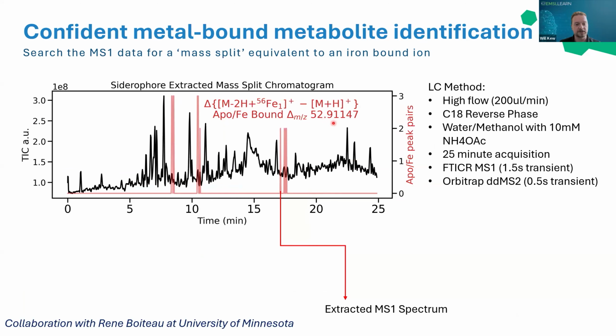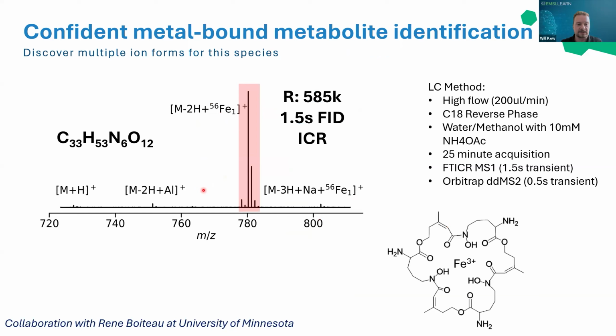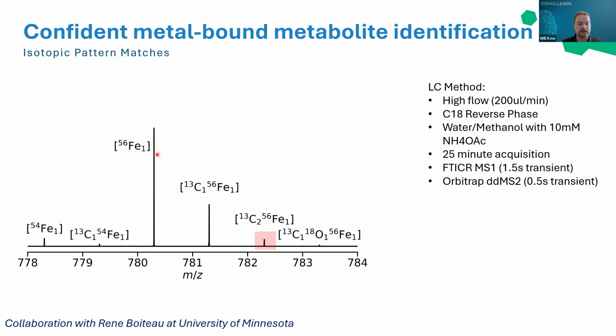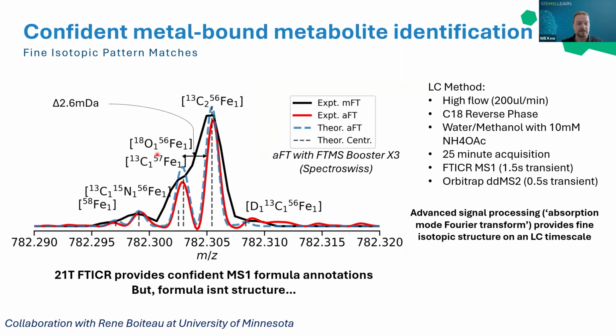52.91147 corresponds to the difference between a protonated ion and an iron-bound complex. We found a handful of those occurrences in this data set. We extract out that spectrum, and you see in a single spectrum, we get our distinctive cluster of peaks for an iron complex. We detected our protonated molecule as expected. We also observed an aluminium coordinating form of the same species, which we hadn't expected to see, which was pretty neat. So with this, we get a molecular formula, and we can confirm it again by zooming in and looking at the fine isotopic structure.